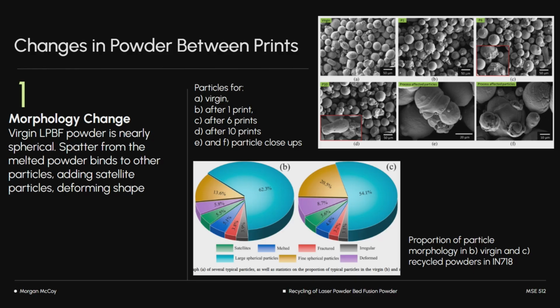Virgin laser powder bed fusion powder is nearly spherical, but spatter from the melted powder binds to the particles, adding satellite particles and deforming the shape. We have a visualization there on the right where we have a picture of the virgin after one print, after 6 prints, and after 10 prints. And you can see that there's more and more satellites on the powder.